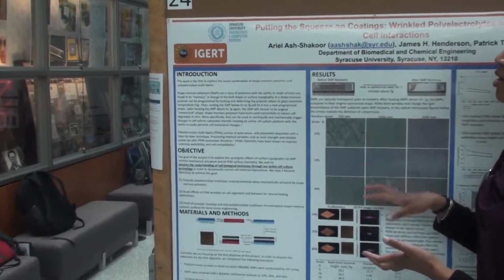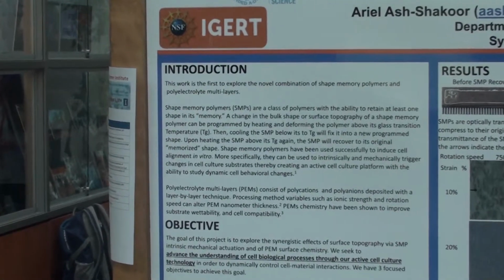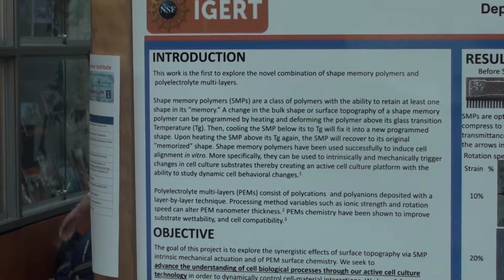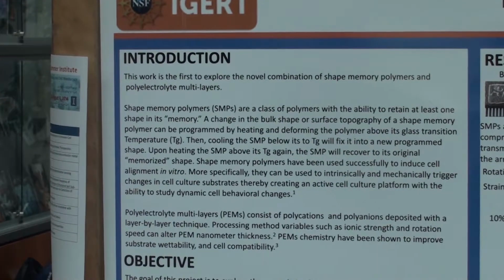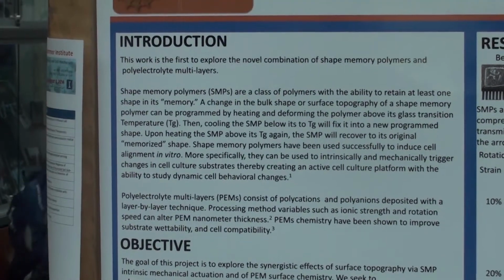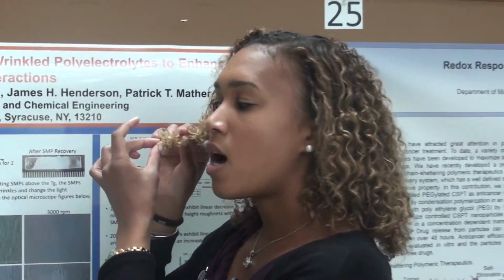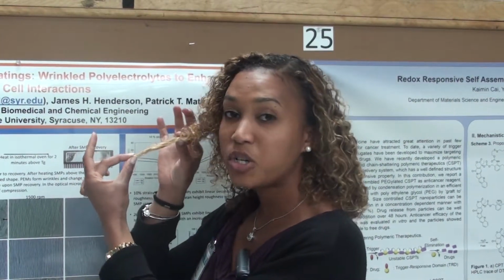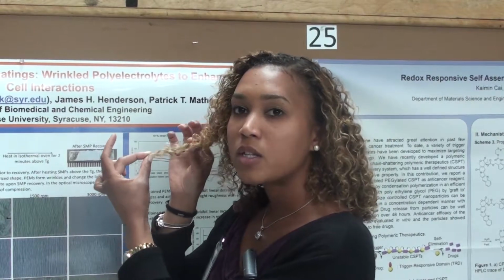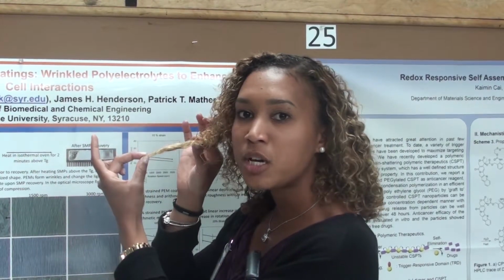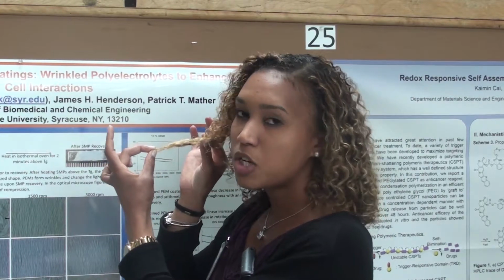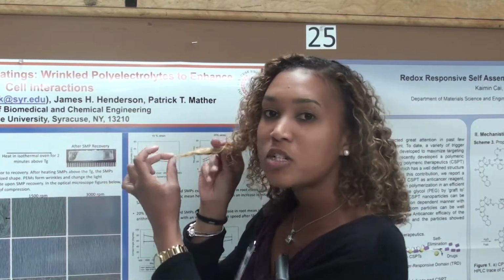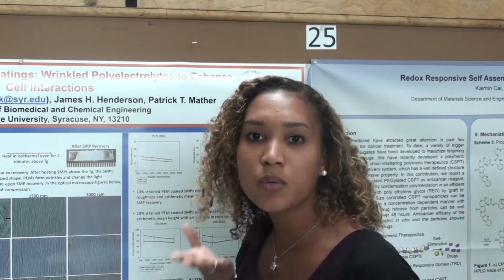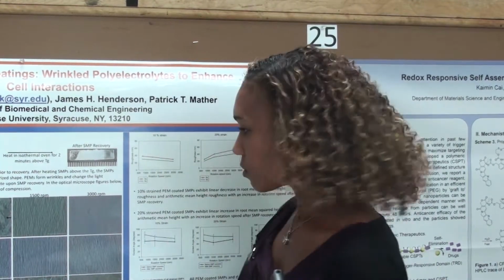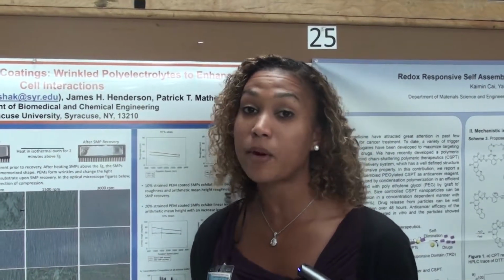So my work focuses on shape memory, mechanical actuation of polyelectrolyte multilayer wrinkling. So you're probably wondering, what is shape memory and what are polyelectrolyte multilayers? If you can imagine that my hair, for example, is a polymer, we can heat this polymer above its glass transition temperature, deform it, so elongate it to a new position, cool it at this new position, and then it will remain at this position. But as soon as we heat it back up again, it will elastically recoil back to its original position. And so that's the basic concept for shape memory polymers.